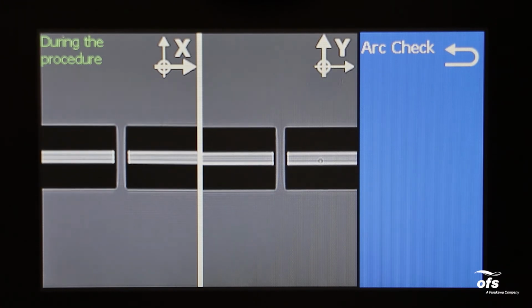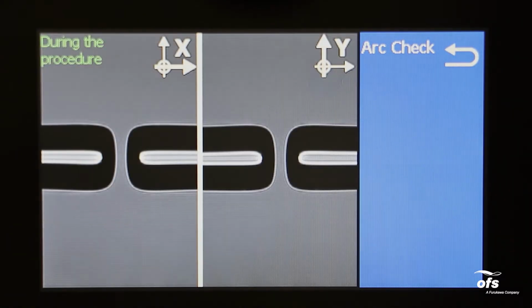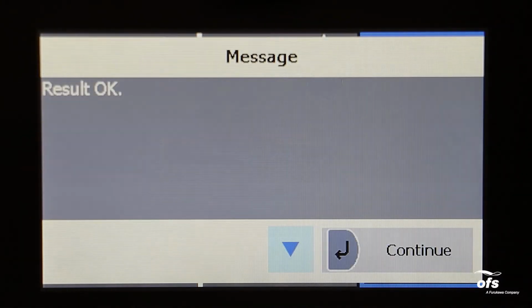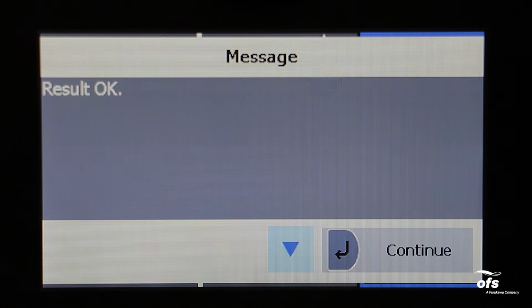The S179 Fusion Splicer automatically feeds the fibers and discharges an arc. During the arc discharge, the fiber feeding motors of the S179 Fusion Splicer remain idle, preventing the fiber's ends from butting. As a result, the fiber ends melt back. The arc check function inspects how far the fibers melt back and the centered position of the fiber.